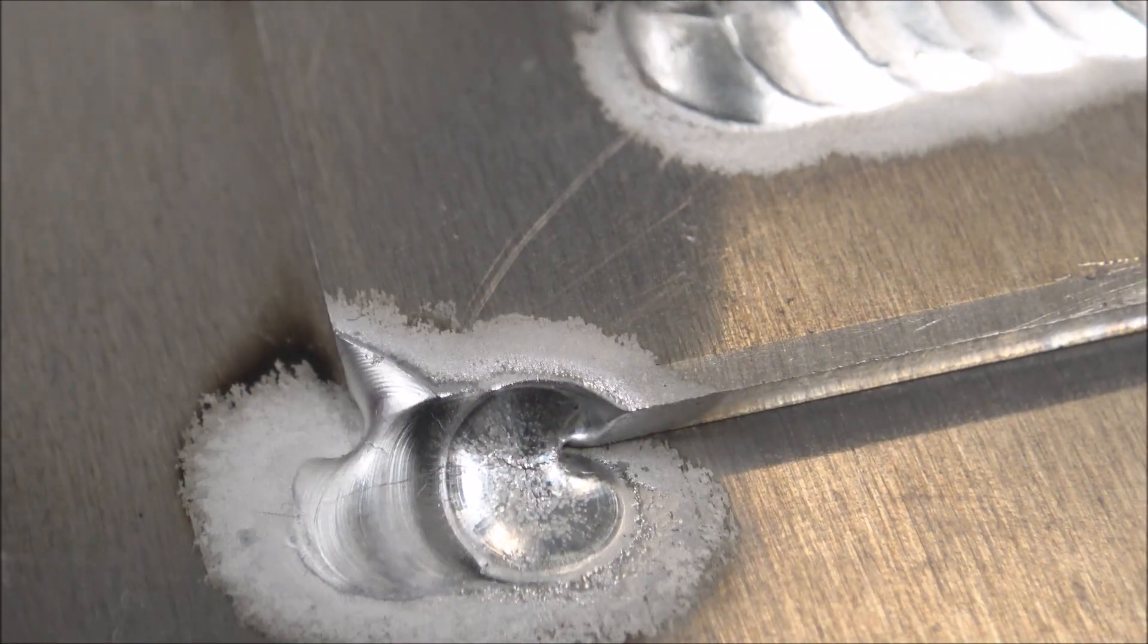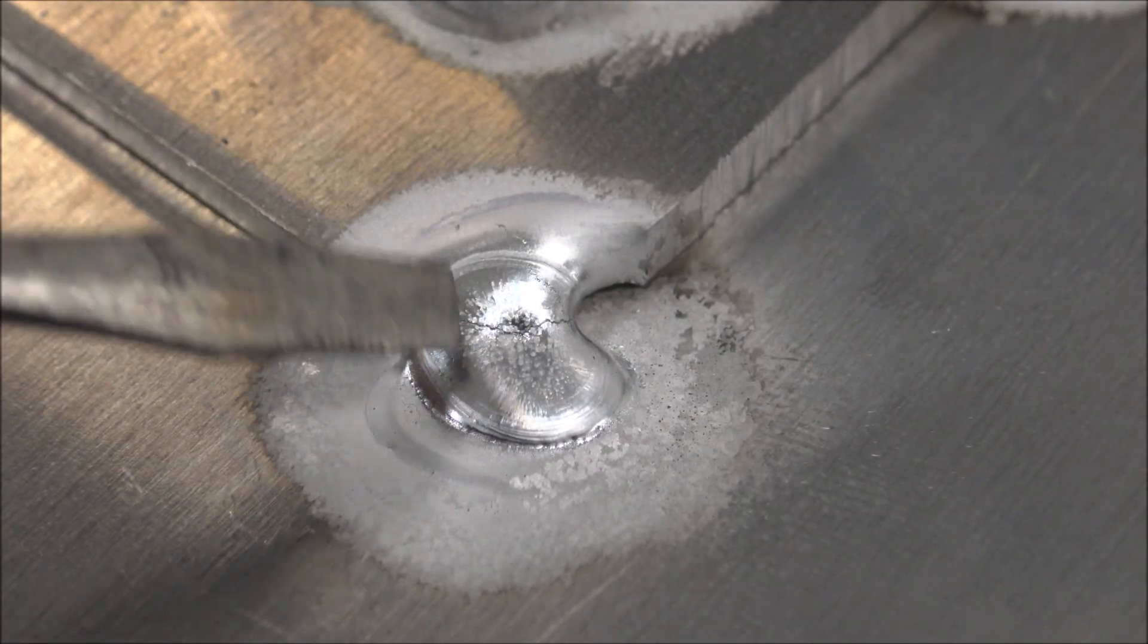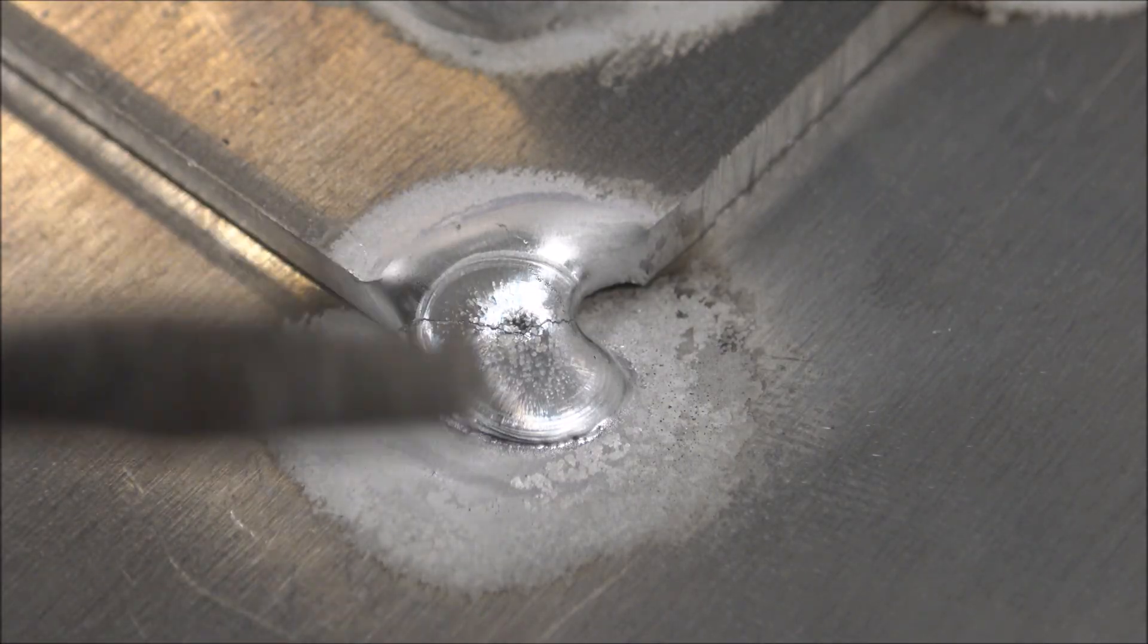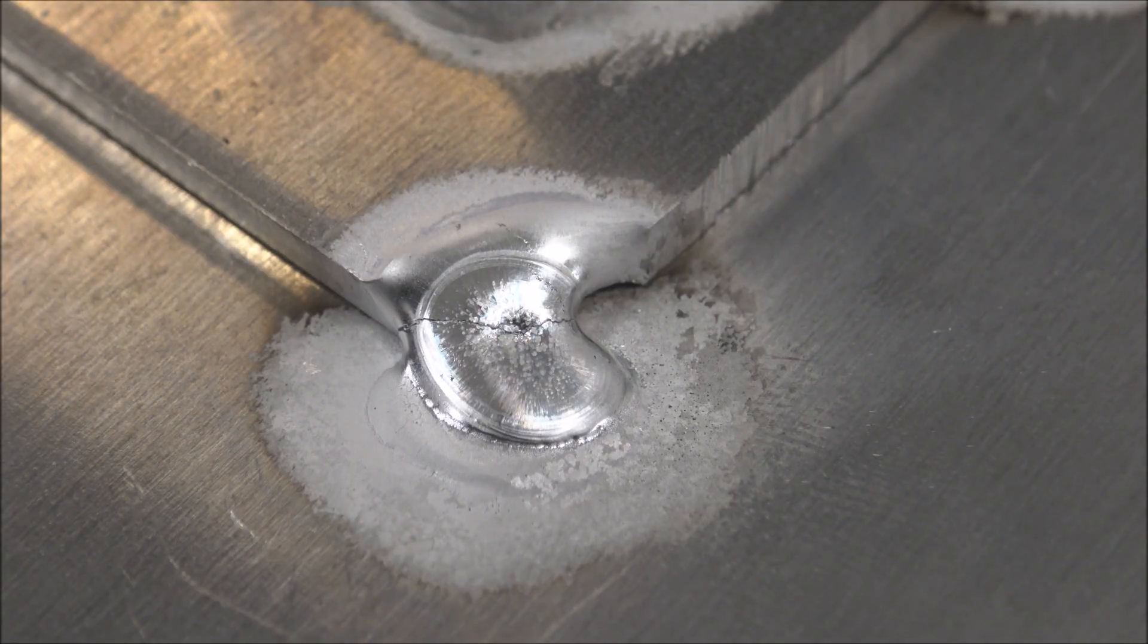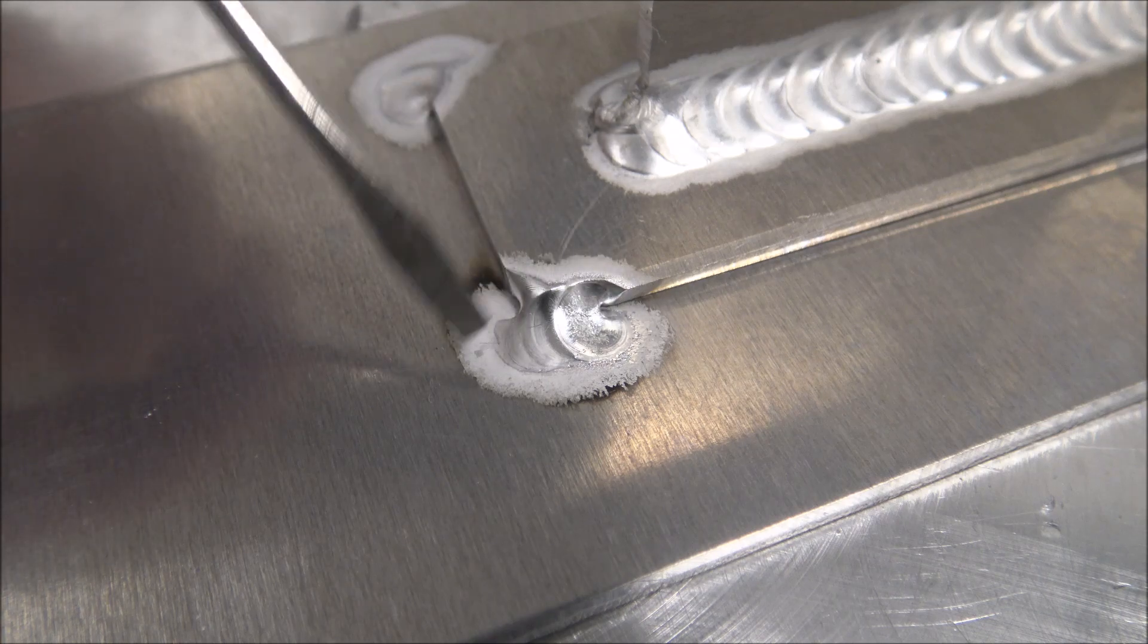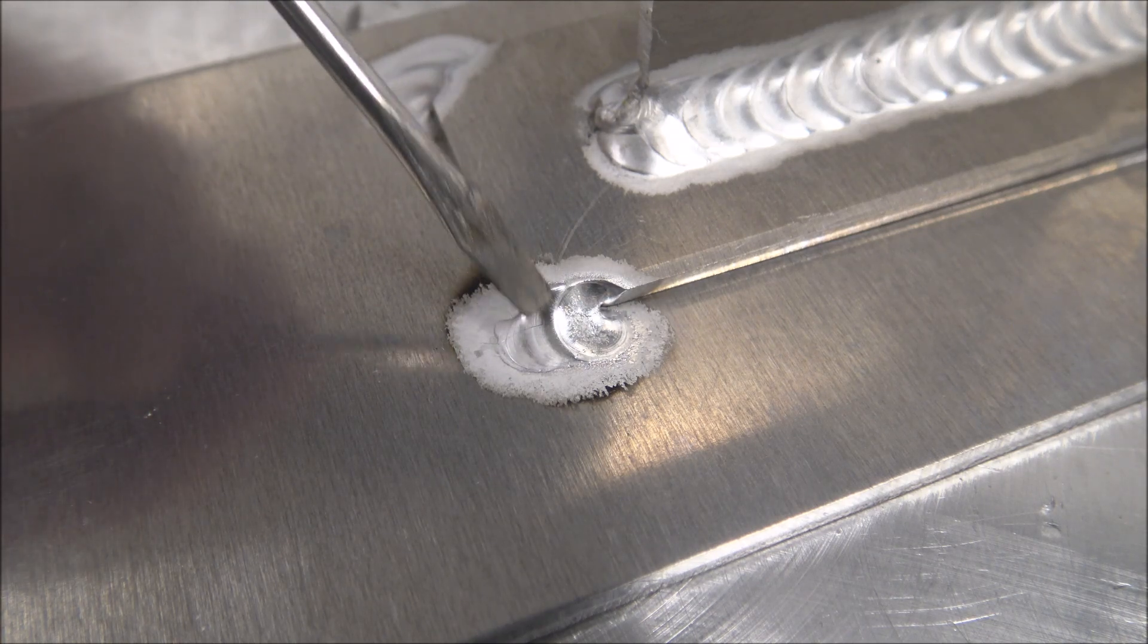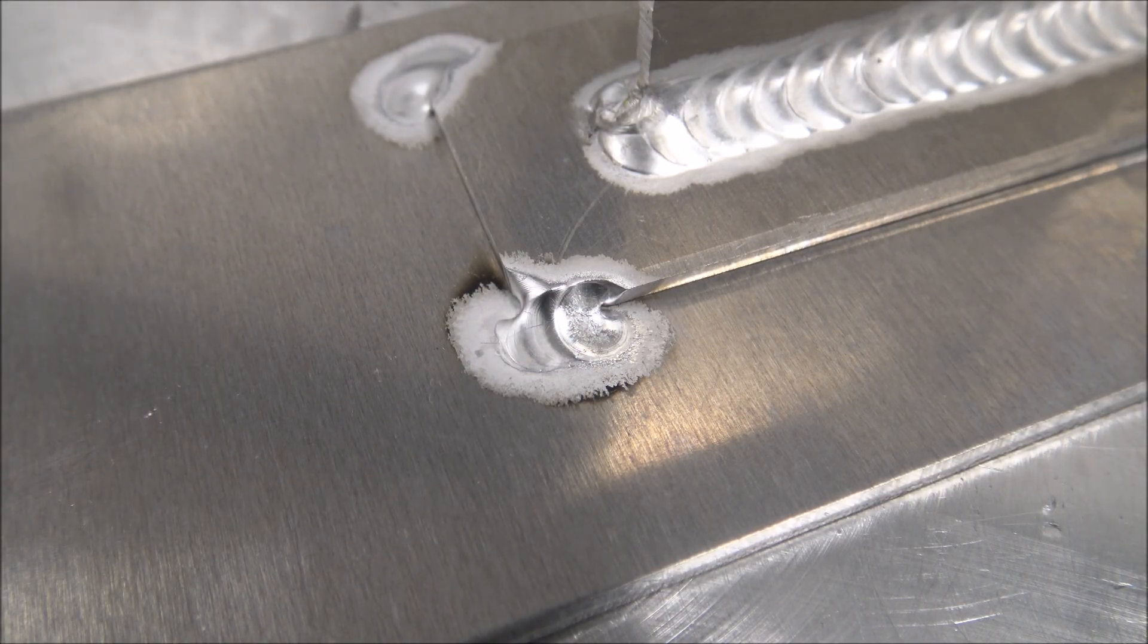If you guys' close-up eyesight is going to crap like mine is, I'm 42 and it hit me pretty quick these past two years. I'll show you in an upcoming video how to get better clear vision while you're welding up close behind your hood. This stuff's 5052 sheet. With 6061 you wouldn't be able to do this. It would just keep cracking away from you. So you're going to have to use filler rod on 6061 typically. I'll get to filler rod tacks here in a little bit on this video.